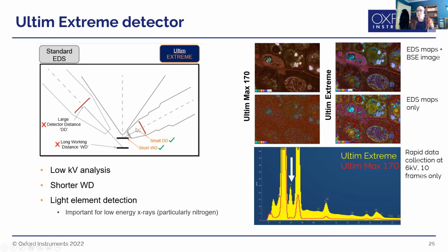Well, it means we've got a much smaller front on our detector, and we can get much closer. Because we can get closer to the pole piece, the working distance is also much better. So you have an optimized working distance of your sample from the pole piece to get the best amount of X-ray signal. Typically that can be 10 or 15 millimeters away from the pole piece, which isn't great for image resolution. By reducing the front end of the detector, we can get closer and bring the sample much closer to the pole piece.